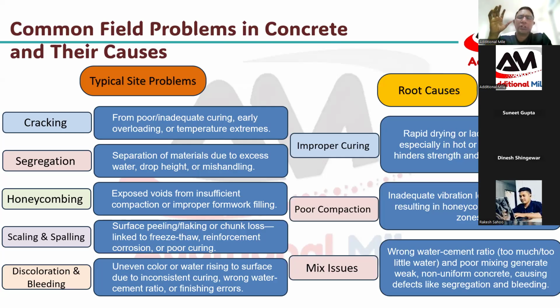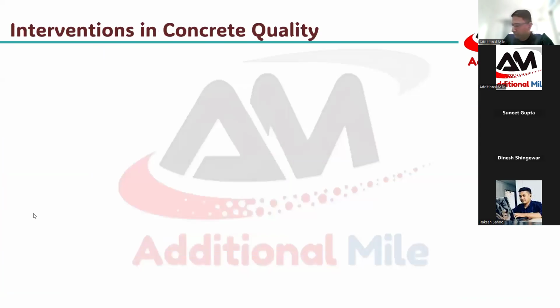So for all these areas, what is the root cause we observed? Improper curing, poor compaction, and some mix issues. Mix issues in the sense, as I told you, aggregates are from different sources, cements are from different sources, or someone has used, as we recently discussed, different types of admixtures or different types of curing compounds. Sometimes what happens, it was a water based curing compound I was recommending to one of my clients, and the client was unfortunately a bit budget oriented. He used the water based curing compound, and he added water to that and diluted it. Just a minute.